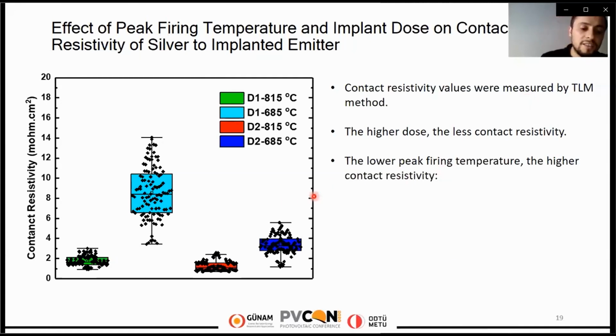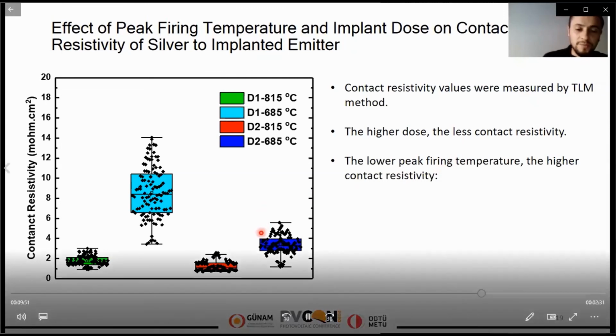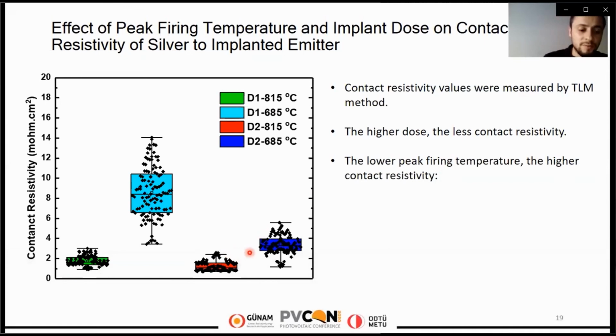Although firing temperature slightly affects the contact resistivity of the high dose, you can see from red to blue, it is more significant in the case of the lower dose. An increase in firing peak temperature results in a decrease in contact resistivity.